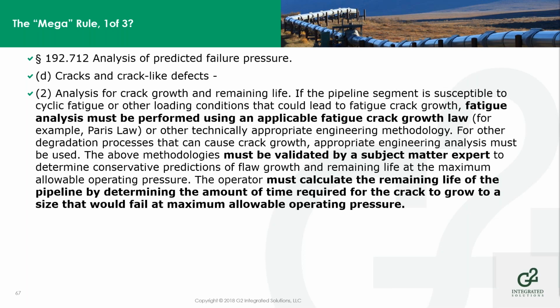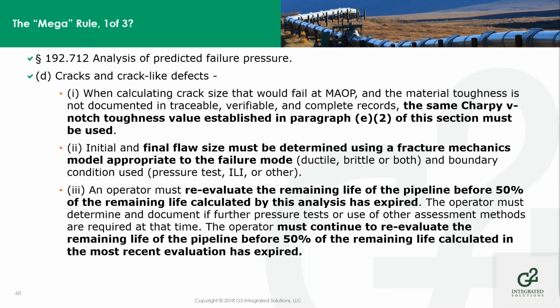For crack and crack-like defects also, the fatigue analysis must be performed using an applicable fatigue crack growth law, and they have to be evaluated by an SME. You must calculate the remaining life of the pipeline, determining the amount of time required for the crack to grow to a size that would fail at MAOP of the pipeline. When calculating cracks that would fail at MAOP and the material toughness is not documented, traceable, verifiable, complete, the Charpy V-notch toughness value established in paragraph E2 must be used. Initial and final flaw size has to be determined using fracture mechanics.